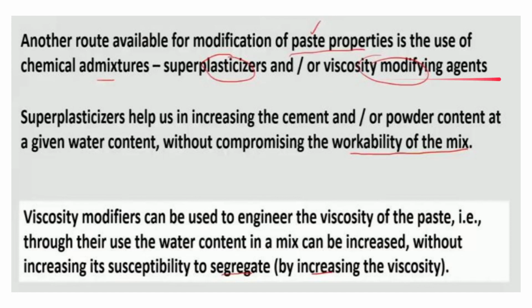Another route available for modification of paste properties is the use of chemical admixtures such as superplasticizers or viscosity modifying agents. These two types of chemical admixtures, superplasticizer and plasticizer, we all know, result in more workability at a reduced water content. So if we want to reduce the water-cement ratio and keep the slump value the same, then we can use superplasticizer. And viscosity modifying agent is basically quite the opposite. It is mainly used for increasing the viscosity, the friction between the materials, so it will not allow easy flow.